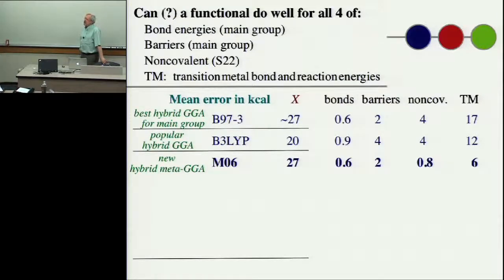But people discovered that these functionals, like the local ones that don't have good performance across the board, were often getting reasonable binding for the wrong reason. It was coming out of the exchange functional, but it's supposed to come out of the correlation functional. So they had large errors in exchange, and it sometimes was giving spurious binding. So they couldn't really get the trends right. They couldn't get good quantitative results. So now it's generally believed that the local functionals do not do a good job.